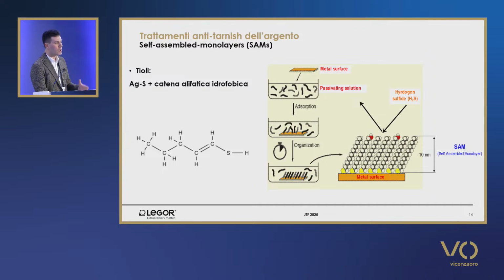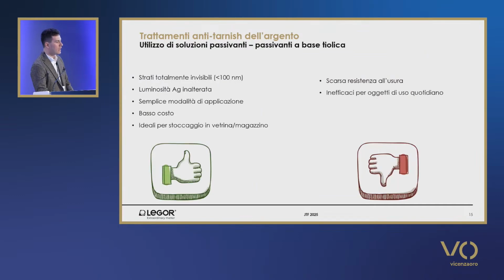are called self-assembled monolayers. These are molecules which interact with a metal surface and can be absorbed and can organize independently as to create a homogeneous layer. In terms of silver, these are very useful because they can bind to the silver surface and they create a connection, a bond, and they make the surface hydrophobe, thus slowing down the absorption of humidity and the interaction of the surface with the sulfur compounds.